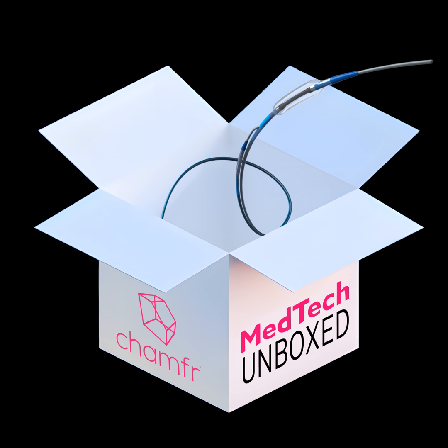Okay. One last question about the shrinkage. Is that something that the customer will spec? Is that an ASTM standard for certain materials? Like what percentage, I guess, is acceptable typically for PEEK? Yeah, so the shrinkage values are typically published by the resin manufacturers, because they'll actually have their resin tested, and there's a variety of standardized tests to calculate what the empirical shrinkage values are. They're very geometry dependent for a lot of the reasons we just talked about, and so they'll typically publish a range.